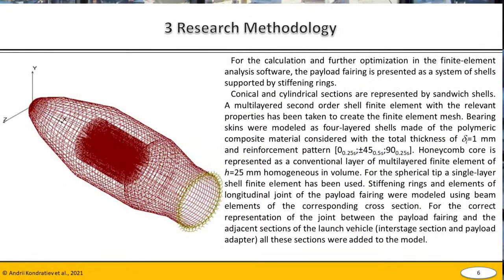For the optimization in the finite element analysis software, the payload fairing is presented as a system of shells supported by stiffening rings. Conical and cylindrical sections are represented by the composite shell finite elements that include 4 layered bearing skins and a separate layer for the honeycomb core modeled homogeneous in volume. For the spherical tip, a single layer shell finite element has been used. Stiffening rings and elements of joint were modeled using beam elements. For the correct representation of the joint between the payload fairing and the adjacent sections of the launch vehicle, all these sections were added to the model.